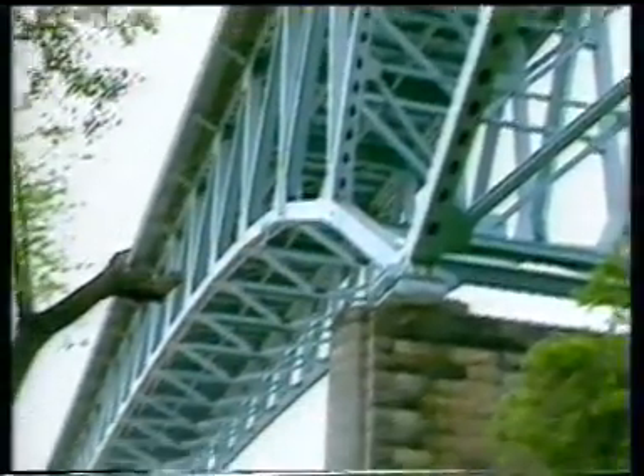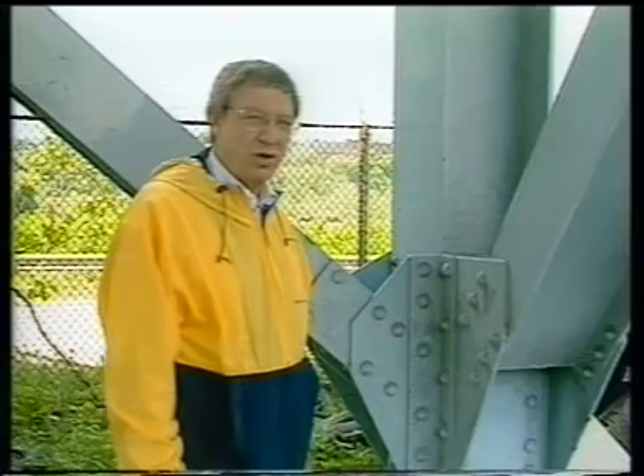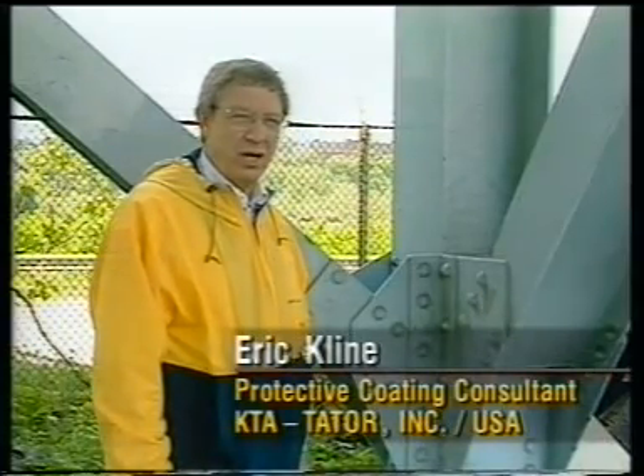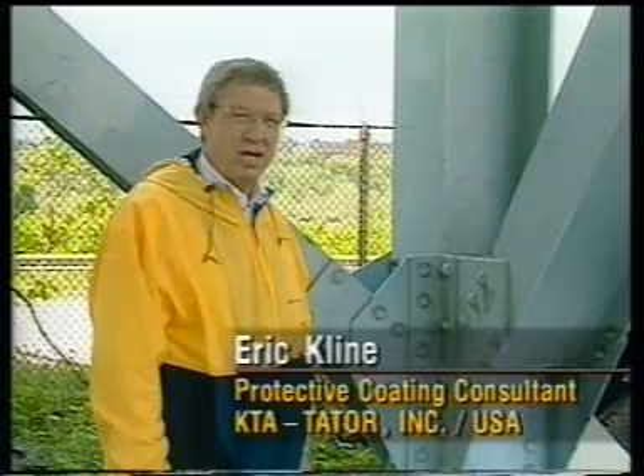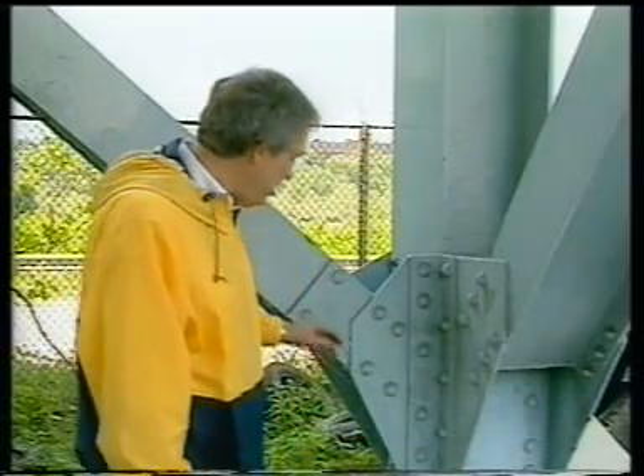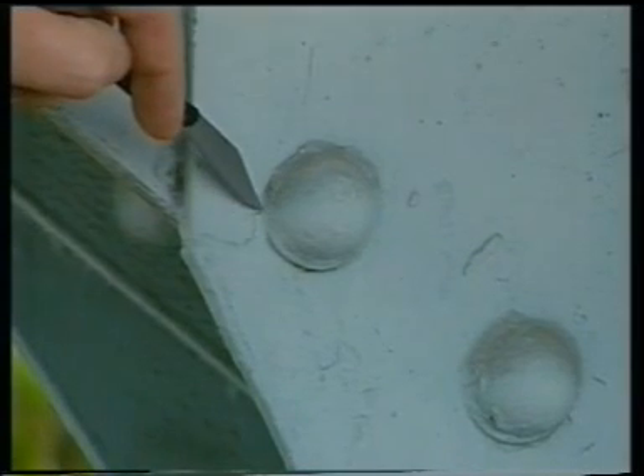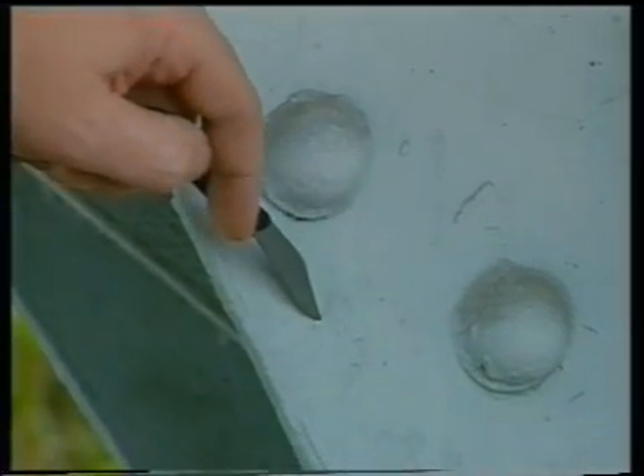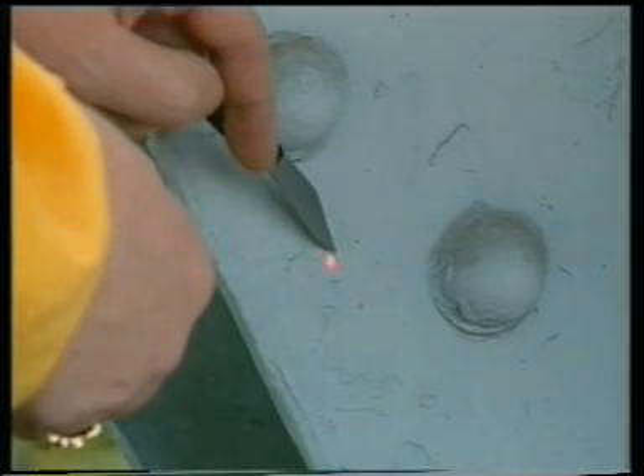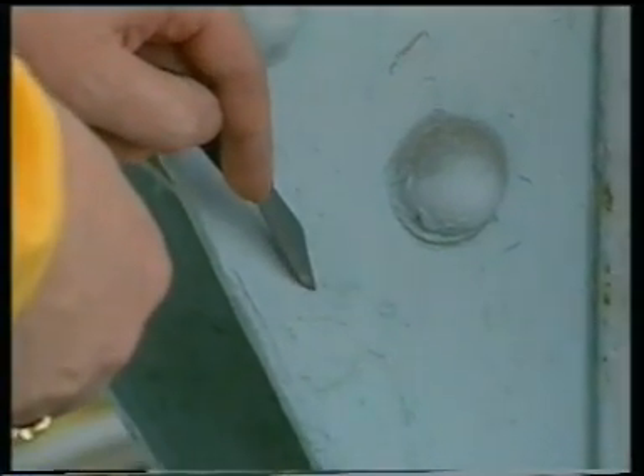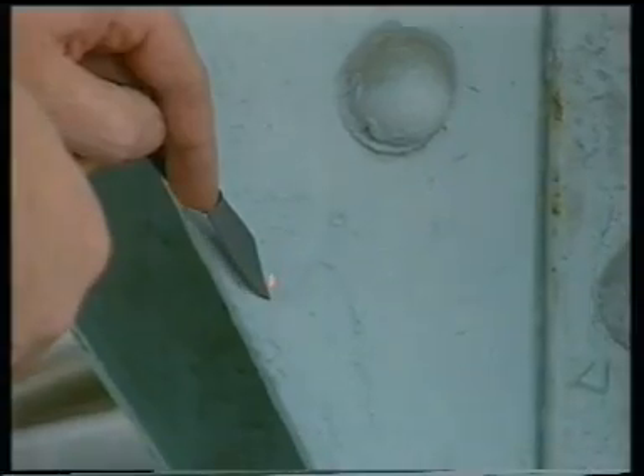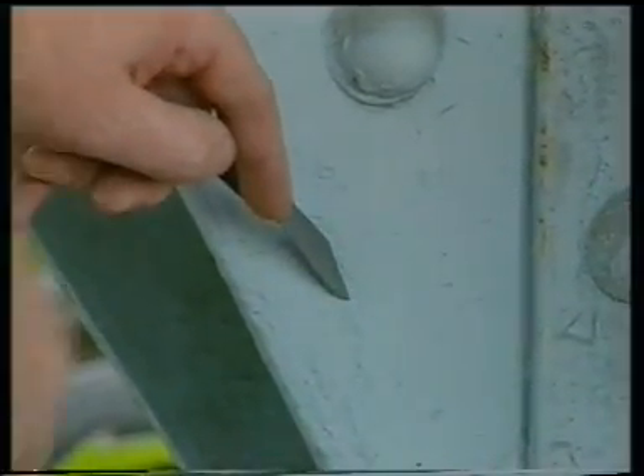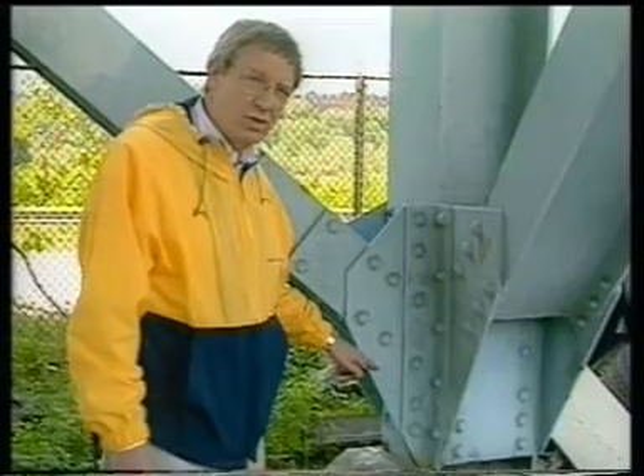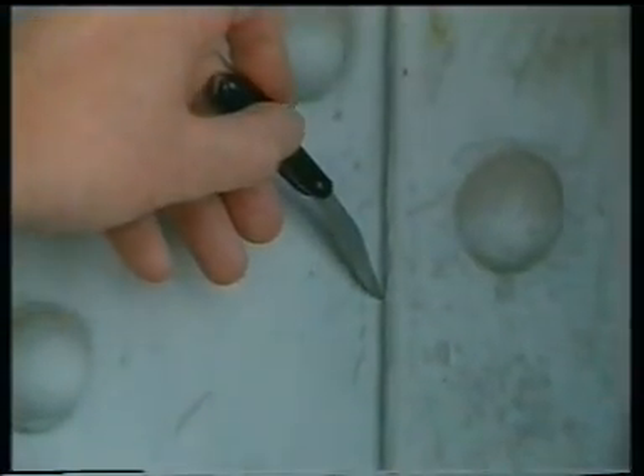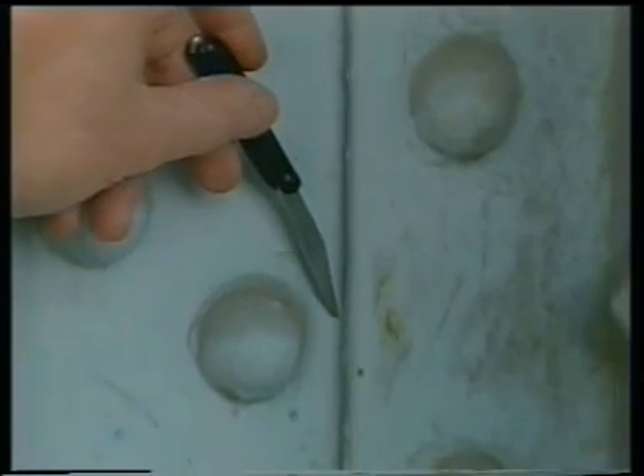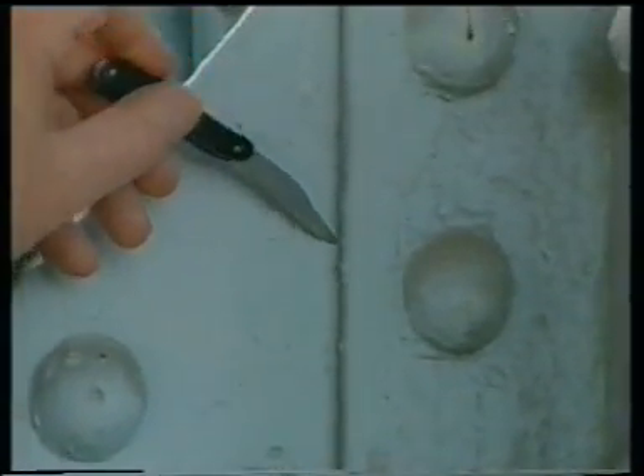We're at the Homestead High-Level Bridge, a bridge that was overcoated about 15 years ago, and we're going to look at some of the areas that were overcoated and see how they're performing. You'll notice that there's a section right here on this gusset plate, and the ridges and shoulders from the old coating where it was fractured in the cleaning process have been sealed by the overcoating system. In the overcoating technology, we try to get sealing along these fractured edges, and this represents a successful application of an overcoating strategy. It's important to seal those edges so that we seal out moisture and oxygen to stop the corrosion process from taking place.